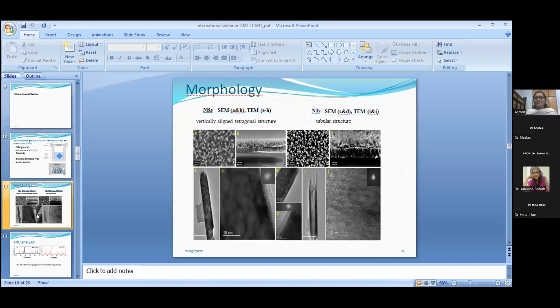Now, towards the morphology of the nanorods and nanotubes, if you look at the top panel of this picture, A and B are the vertically aligned tetragonal structures of the nanorods. And after etching, we can see C and D, the etched nanorods. We can see a very nice hollow structure of the nanotubes, which are vertically aligned. Now, if we look at the bottom panel, we have 10 images, and from E to H, it has the nanorods, and I and J represent the nanotube. So a single nanorod, you can see, is a well crystalline nanorod. We can also see the electron diffraction pattern.